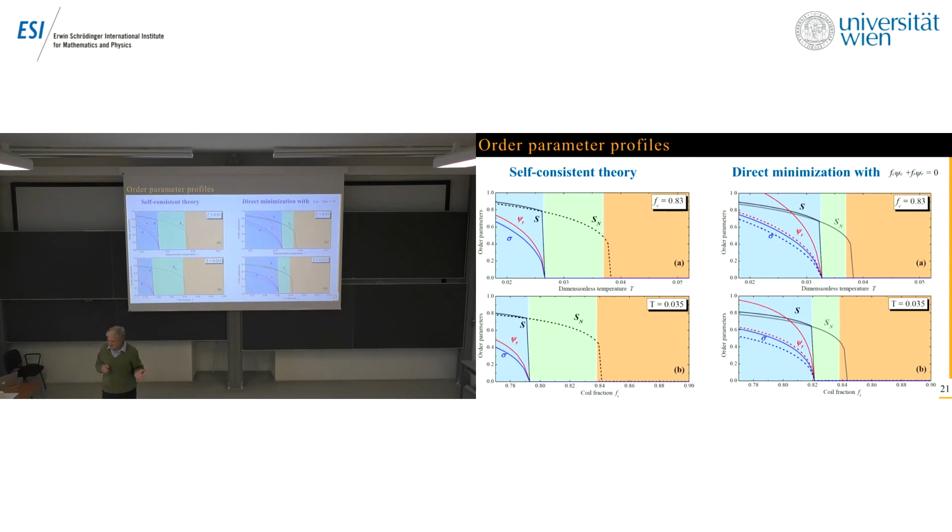Right, so you have to use Lagrange multipliers to get everything correctly, because there is a self-consistency equation for order parameters which can be derived in the formalism of Lagrange multipliers, and this prevents it from going above 1. So it can be rigorously shown that it's less than 1. And if you use the simplified approach, then you mix all equations, and you lose this self-consistency.